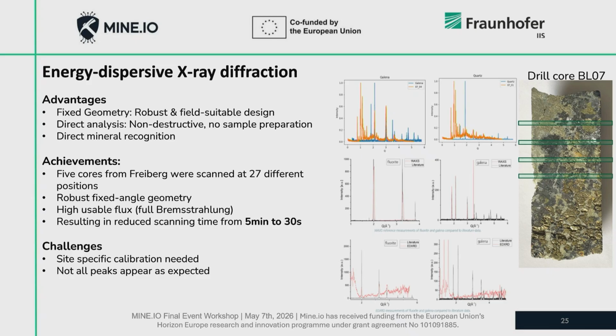The second drill core analysis tool is the energy dispersive X-ray diffraction. Compared to standard X-ray diffraction, it uses a fixed geometry, which makes it a lot more robust and even suitable for the application in the field, in contrast to the standard X-ray diffraction that requires lab conditions, very sensitive devices with goniometers and things like that, which you cannot use in the field. But the energy dispersive X-ray diffraction uses the fixed geometry to overcome that problem. It is also a non-destructive technique, and aside from basic cleaning of the samples, there's no further preparation needed.